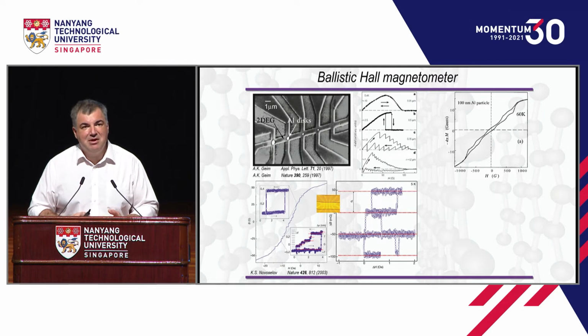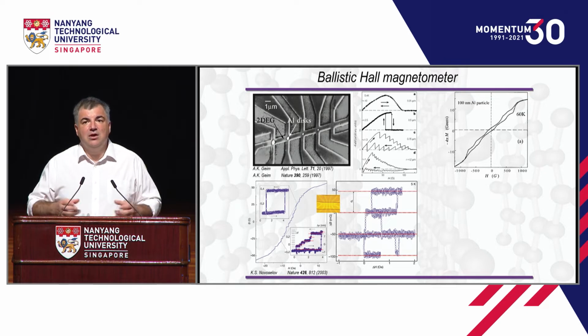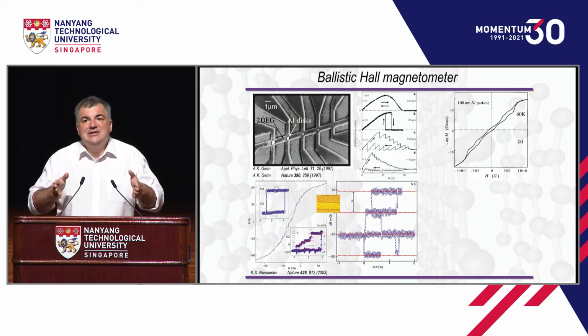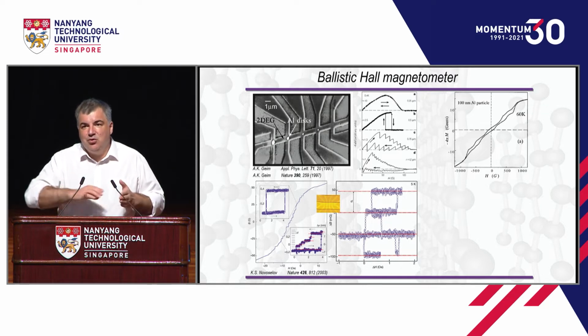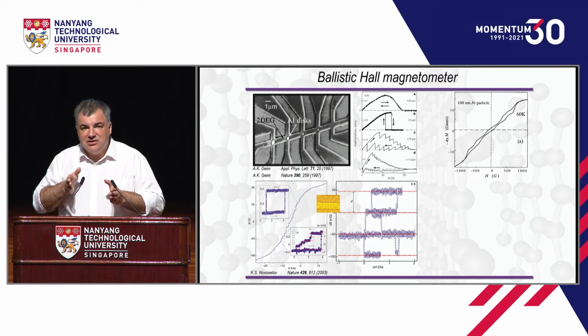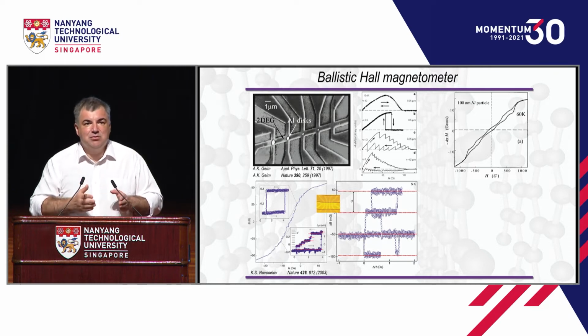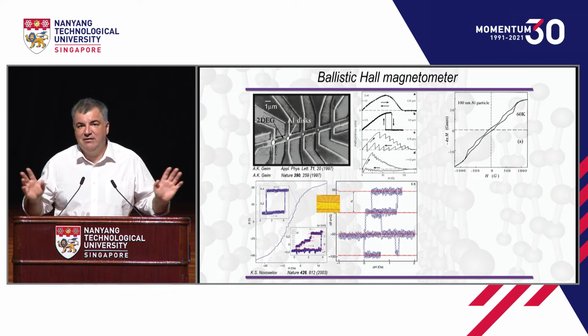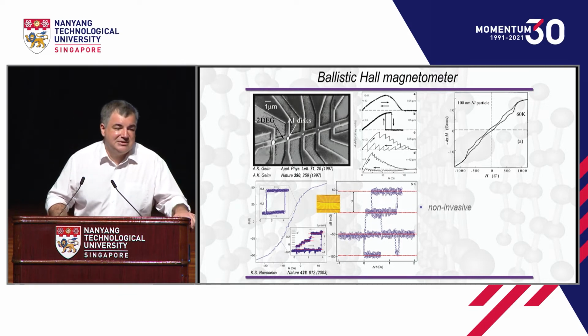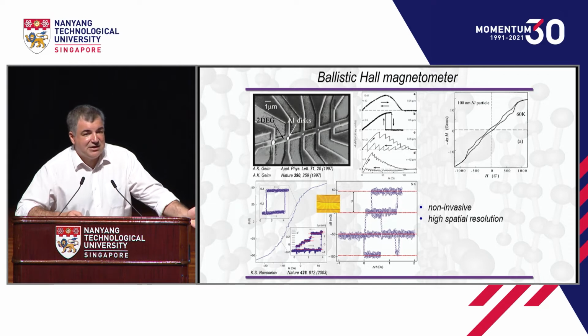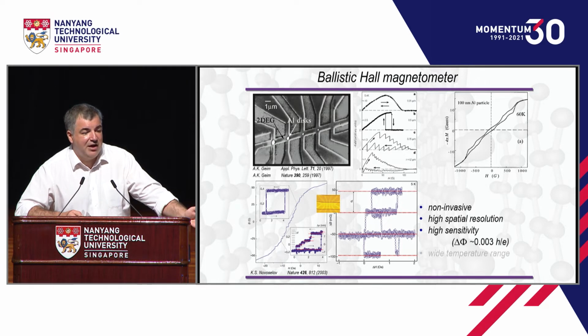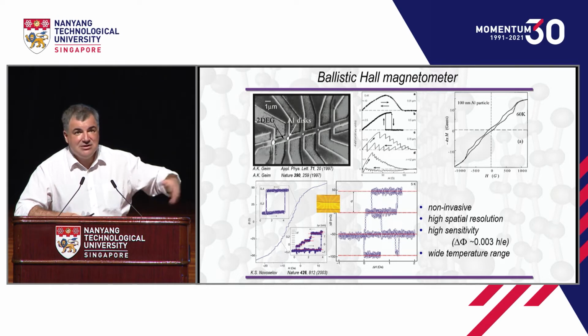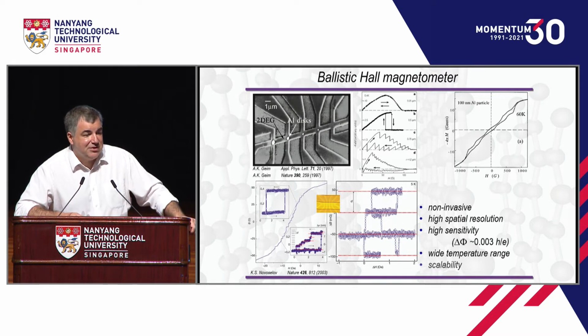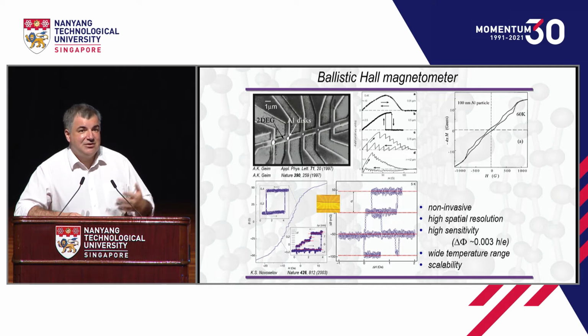So the sensitivity of the method can be very high, and the idea here is that you basically take a Hall sensor. A Hall sensor is just a wide piece of metal where you send current, and then under magnetic field, this current, due to Lorentz force, starts to bend, and it creates the Hall voltage. Very, very simple method. But then it's non-invasive, and it can give you high resolution, but very high sensitivity as well, and it works in a very wide temperature range.